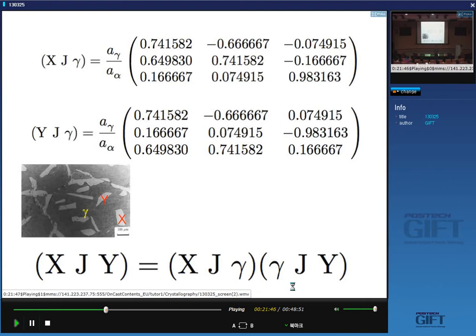Nucleation. Yeah? So the fact that you have to create interfacial area when a particle is very small, that's a very large cost because the surface to volume ratio is very large. So the activation energy for nucleation varies with the cube of the interfacial energy, which means that if you reduce the interfacial energy, then nucleation is more likely. So when a system is trying to transform, it's possible that many, many orientation relationships could form, including random ones. But the ones which are likely to form are the ones which minimize interfacial energy. Okay? So that's one reason why we get reproducible orientation relationships when we get solid-state transformations.